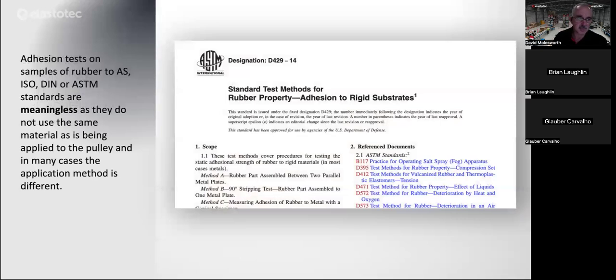Sometimes in specifications, people will ask for adhesion tests to be done to ASTM or Australian standards or ISO standards or some other international test method. This is a completely useless exercise because the sample preparation and the method of producing the sample is completely different to what's going on the pulley. To understand what's actually happening on the pulley and be confident you've got the right bond, you must have the samples you're testing made from the same batch of materials as what has gone on the pulley, and they must be cured in the same way at the same time.